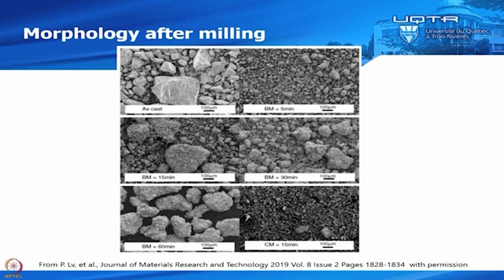So this is the morphology of our powder after ball milling. This is as cast. So we cast the sample and then we just crush it with a mortar and pestle. And you have this big chunk of iron titanium. And then we ball mill it for 5 minutes, 15 minutes, 30 minutes, 60 minutes, and this is cryo mill. So you see that after just 5 minutes of ball milling, you have a huge reduction of particle size. But if you continue to mill for 15 minutes, you see that you have agglomeration of smaller particles.